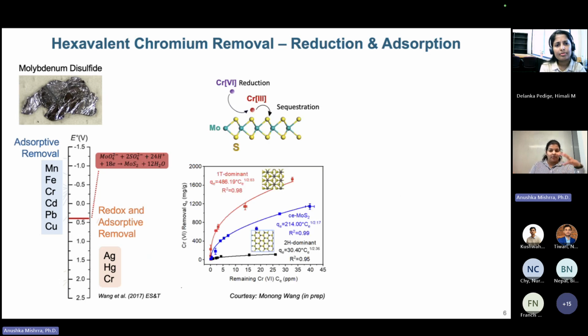There is established work on how chromium 6 can be reduced to chromium 3 - that's the attractive property of MoS2. Molybdenum disulfide can undergo a redox process with chromium 6, and the resulting chromium 3 becomes non-toxic when you handle the final product after the reaction.